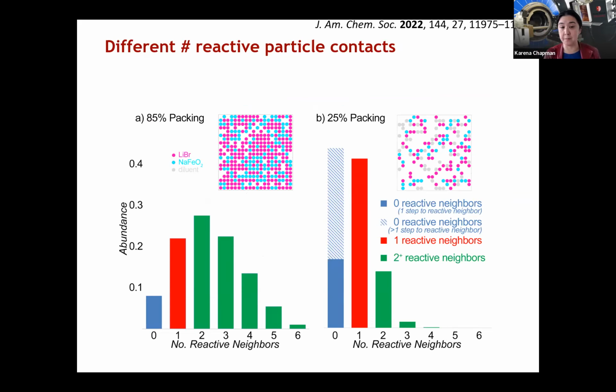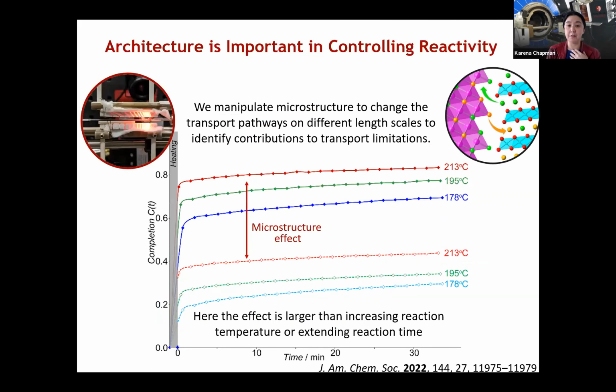If we just had that lower packing case, then actually about half of our particles were not sitting next to a particle that it would react with - it was sitting next to a particle that was like itself. So this says this is actually a pretty important effect in governing how much reactivity we see, if any. This microstructure effect, or architecture, is more important than the temperature in governing this particular reaction, which is limited by transport - something that we perhaps hadn't codified before during this experiment.